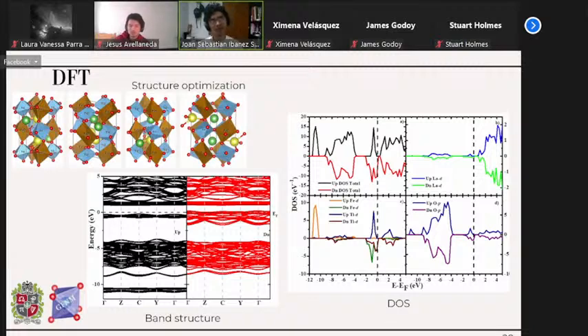To see the stability of our sample, we measured how the energy changed when we changed the positions of both the calcium and the lanthanum on the cation position, and found that the structure with the least energy was the first one, at the top left. From this structure, we found that the material behaved a little bit like an antiferromagnet.